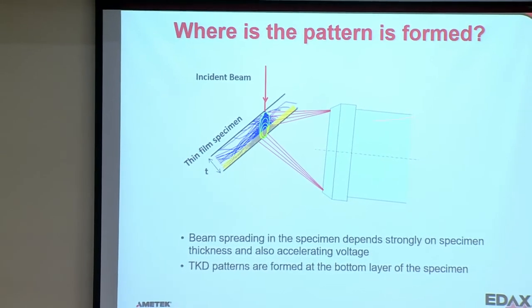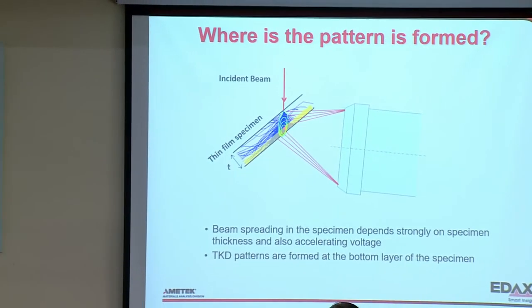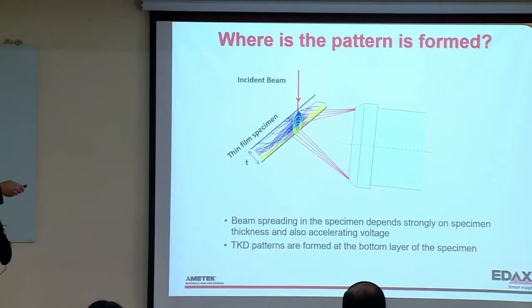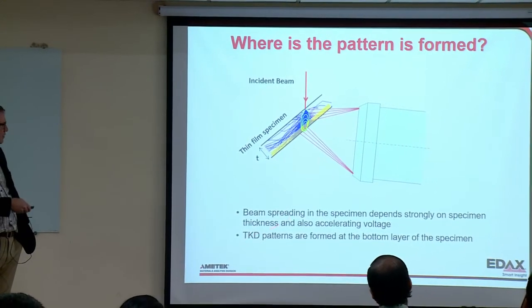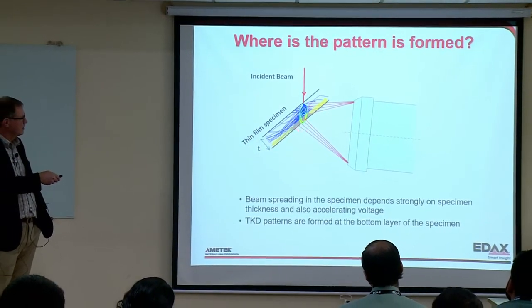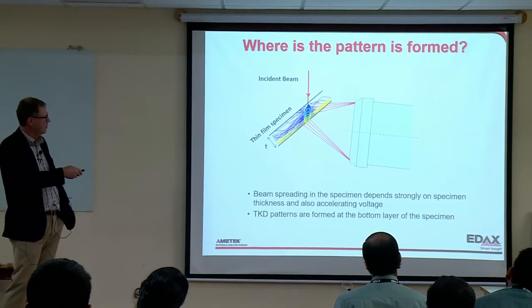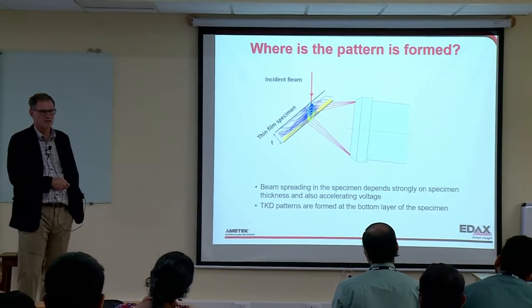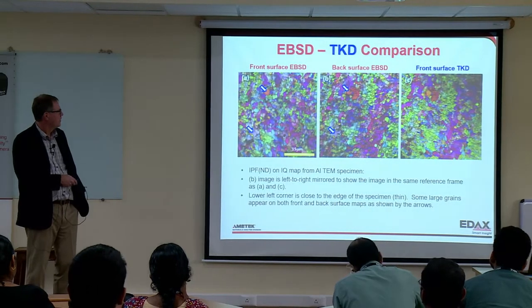Now, the important part here is where is this pattern formed? You have the incident beam, you have diffraction, or scattering, as you go through. But the important thing is the actual signal is created here at the exit edge of the sample. And you can see that here.